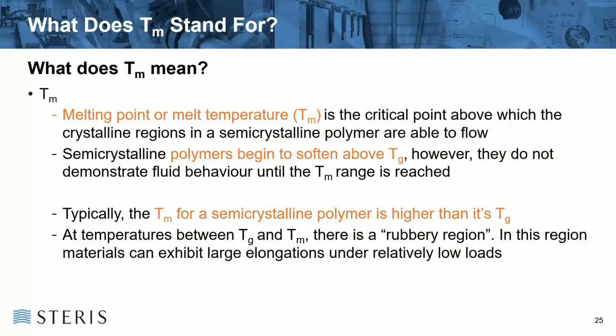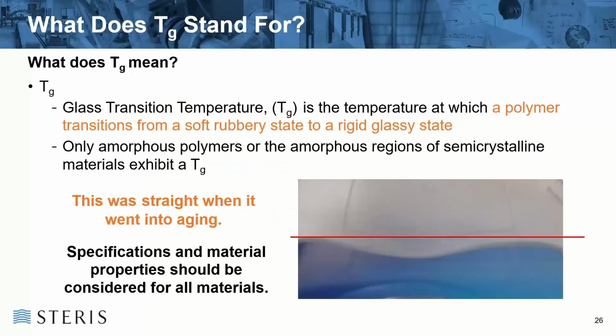Okay, the TM for crystalline, semi-crystalline polymer is much, much higher than the glass transitioning point, or TG, for a particular product. We'll have a little bit more look into that shortly. The glass transitioning point on a polymer is the transition point from a soft rubbery state into a rigid or glassy state. So when you're forming your actual tray, or forming your pouch, or forming your actual product, it's the temperature that the material becomes solid, and vice versa. If you're overheated, it will actually start to melt again.